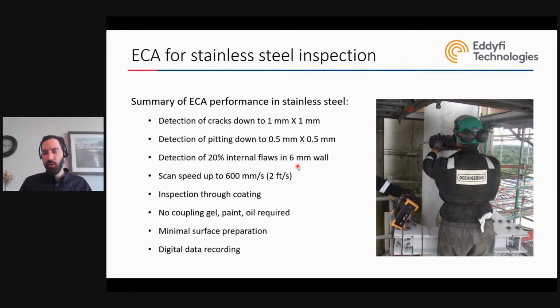If we have a 20 millimeter wall, we can build something custom, something different that will penetrate even more. But then on the other hand, you will always also lose resolution. So there's always a trade-off between how much penetration of the wall you do and what is your resolution for small flaw detection.